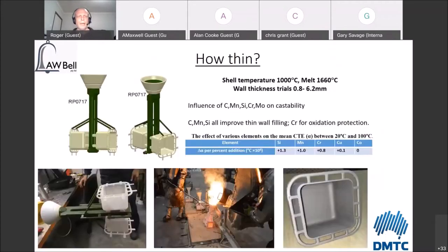So where we started with this project was looking at how thin you could actually go, and what we did was we were using an SLA printer to print the shapes that we were going to do. So we weren't using wax preforms; we were using SLA plastic preforms. We printed these small boxes, and these are in dimensions of around about 10 centimeters by 10 centimeters by 10 centimeters, and they have 5 different wall thicknesses.